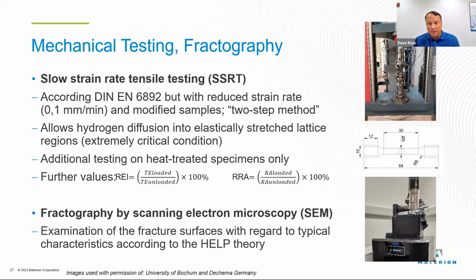And then the values we looked at were the relative elongation and the relative reduction in area. That means an elongation is how far that sample is going to stretch before it breaks. So it's the total plastic deformation, and the reduction in area is how narrow does it get effectively where it fails? How much does it neck down? And so loaded versus unloaded means at 100%, absolutely no effect.